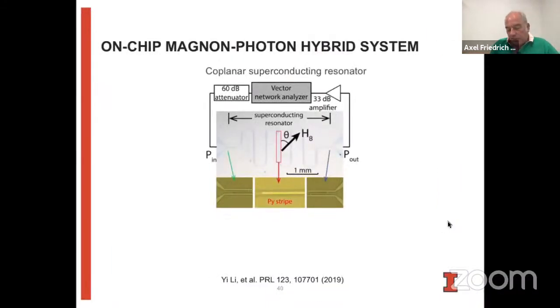So we were interested in trying to see if we can do this in an all-planar architecture. And so the way how we did this is we made a superconducting resonator as a planar device where we have a ground signal ground microwave strip line that we terminate capacitively at its end. So that sets our resonator length. And then in the middle, we then integrate a thin film magnetic system, which in our case is permalloy.